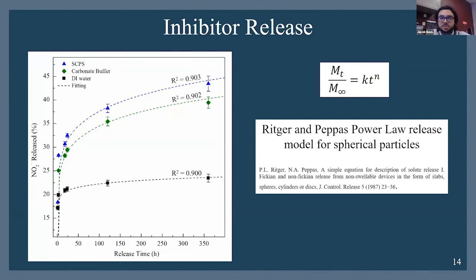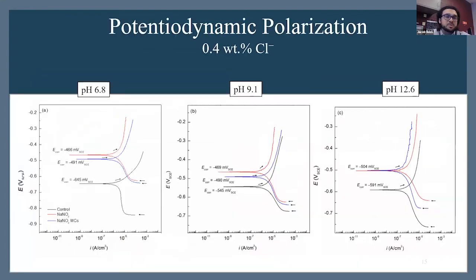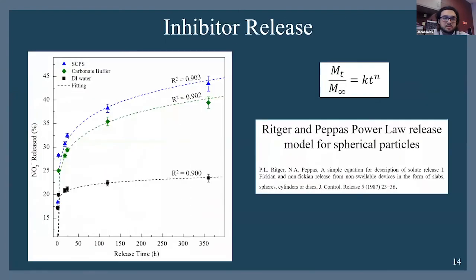the nitrite molecules to a dye to see with the UV-vis, and it was found that the release was able to be modeled by the Ritger and Peppas power law release model for the spherical particles, and we found good correlation there to be able to predict how much inhibitor we can release from these microcapsules over the long term.